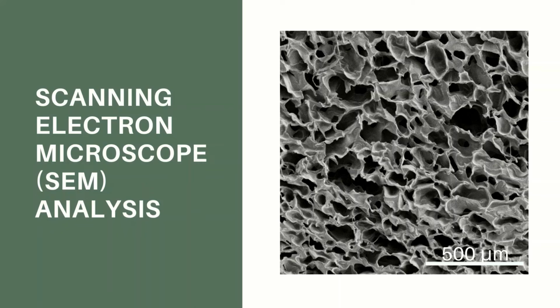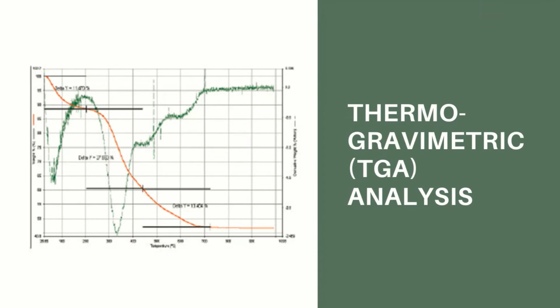The SEM micrograph at 500 micrometers showcased the morphology of the 3D porous scaffolds of collagen hydroxyapatite composite, revealing a significant porous structure.